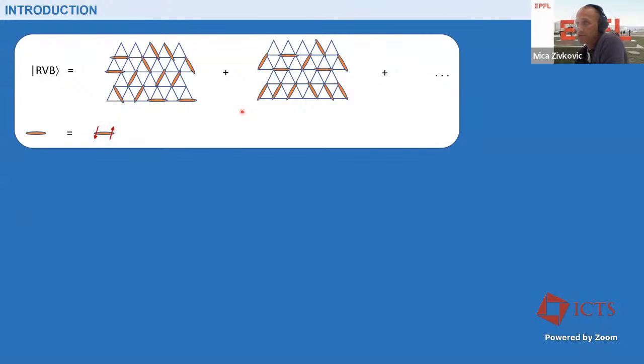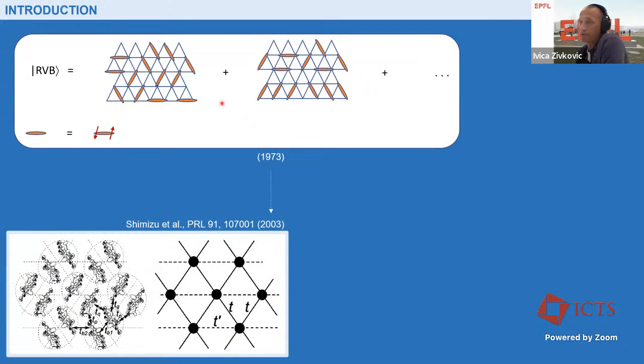So in this case, a long time ago, Anderson postulated the idea that on a frustrated triangular lattice, you will have this entanglement of singlets, which then fluctuates on different bonds. But then it took basically 40 years to properly realize that model, right? So then in 2003, this organic-based triangular lattice compound was synthesized and proved that it shows really spin liquid behavior.